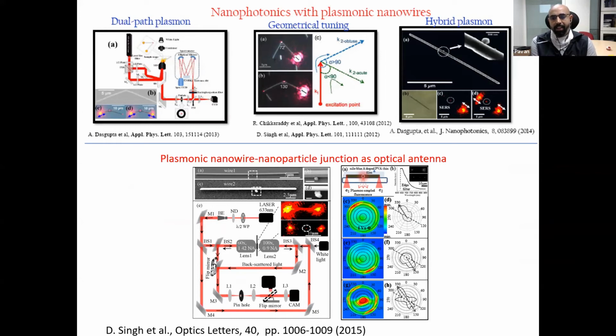We have utilized propagating plasmons not only on films, but also on various different nanowires. For example, silver nanowires is something we have been studying for a long time, where you excite the plasmon and it creates very localized optical excitations, but also a kind of quasi one-dimensional delocalization, which gives rise to very interesting hybrid plasmons, where you can have a localized plasmon from the particle and a propagating plasmon from the nanowire. This creates a unique opportunity to study such interactions in such optical and optothermal fields.